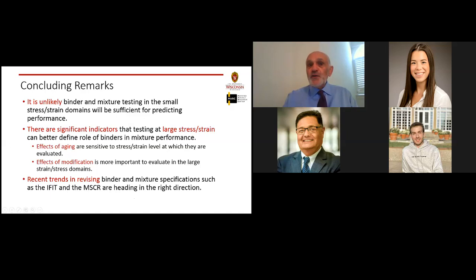it is really, in my very humble opinion, unlikely after all of these years, and I was involved in the original development of the G-star and the sine delta, but I'm totally convinced that it is unlikely that binder and mixture testing in the small stress or strain domains will be sufficient for predicting performance. The issue is, performance is a high strain phenomenon. You cannot get our pavements to fail at very small strains or small stresses.